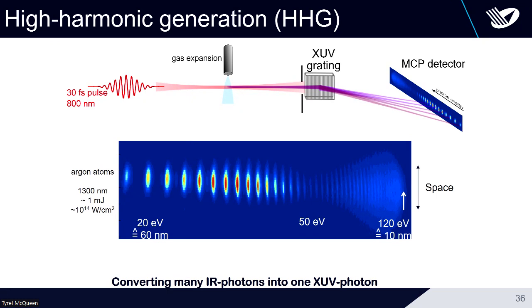Oh, now we go very deep into the physics. In the process of high harmonic generation, I'll show that on the next slide also, there's a photoelectron generated that's laser driven, accelerated, and recombines. And that recombination step is the time inverse of photoionization. So you get characteristics of photoionization. It's an atomic structure effect of the generating atom, basically, that is underlying that. That was by no means trivial. There were a few very important papers in PRL about 10, 15 years ago that elucidated the origin of that minimum.